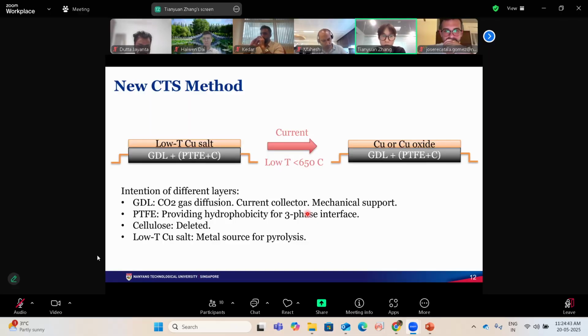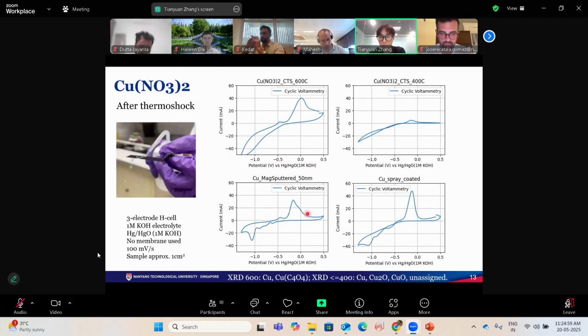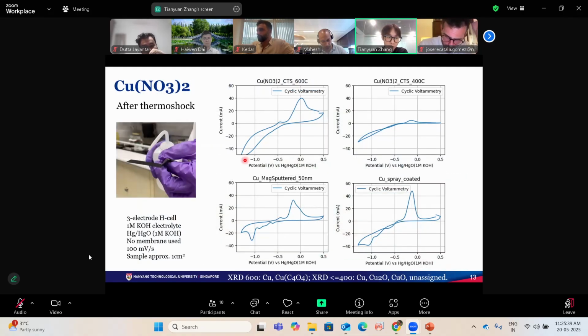So we have to find a new copper salt with a low decomposition temperature, because copper chloride needs a higher temperature than this limitation. So we started to use copper nitrate, whose decomposition temperature is around 200 degrees. And you can see the CV test looks very promising and good compared with the standard sample. The peak is higher, and it illustrates that the catalytic activity is higher. And also you can see this video. We also tested the hydrophobicity of the samples after CTS at 600 degrees. It still remains hydrophobic, as you can see.